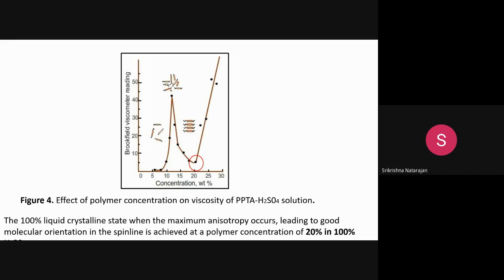Okay, so here this liquid crystalline nature, why are we interested in this liquid crystalline nature? Because it has to achieve this polymer dissolution, the particular spinning dope, where the 100% liquid crystalline state is achieved. That actually leads to the molecular orientation in the spin line. Okay, and that happens only when the viscosity is at this particular concentration. You can see here around 20% concentration, the particular viscosity, whatever is achieved, at that concentration only this liquid crystalline nature is observed. That is what is shown in this graph.